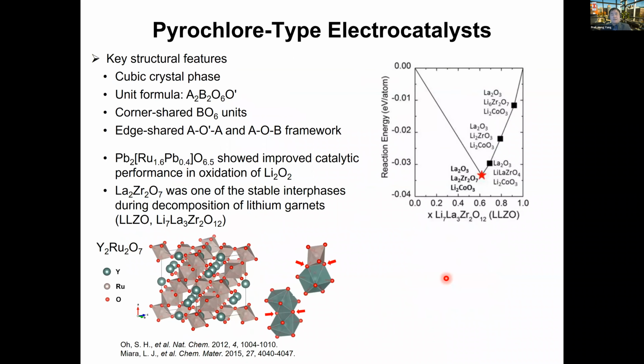So how do we get started with the pyrochlore type? Besides the original evaluation, we tried to introduce defects, either vacancy type or excess oxygen, in comparison with the perovskites. This paper actually inspired us to some extent. This is from Ceder's work that focused on lithium batteries, and they mapped out different types of solid state structures. It turned out this A2B2O7 type is one of those. So we were looking for possible stable structures to begin with, and that's where we got started.